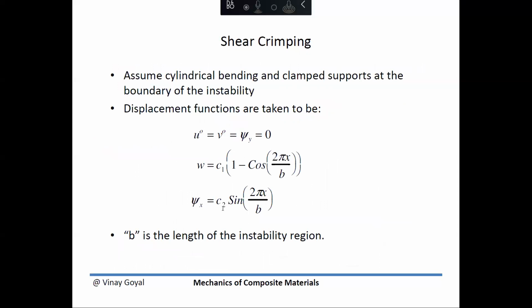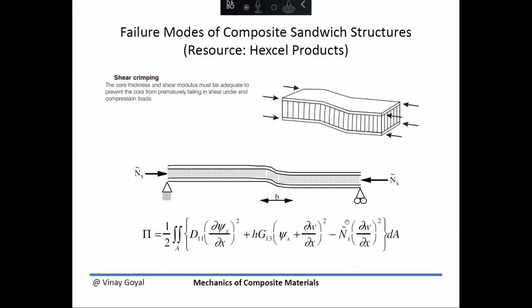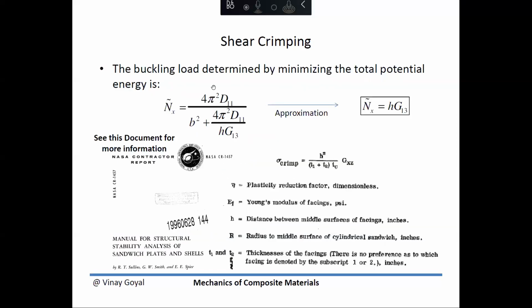So substitute these approximations into this equation. Take the derivative of pi with respect to C1 and C2, and then you're going to be able to solve for the buckling load. That buckling load is this one right here. b is the zone of the shear crimping. And then you have here an approximation that you can make. You don't want the in-plane stress resultant to be greater than the thickness times G13, the transverse shear modulus. h here is the distance between the middle surfaces of the facings, or the core thickness. Here, there's another formula from the manual for structural stability of sandwich plates and shells.